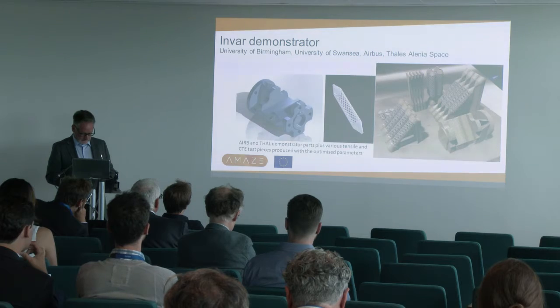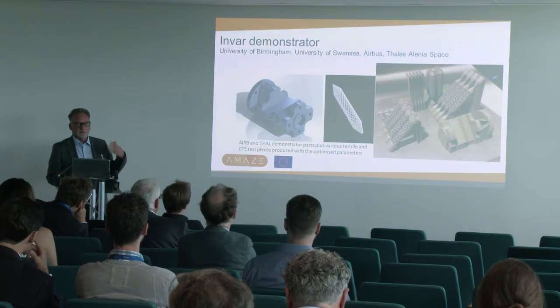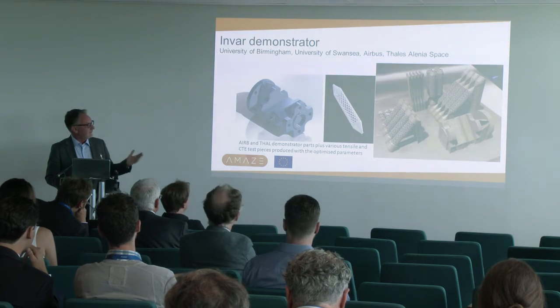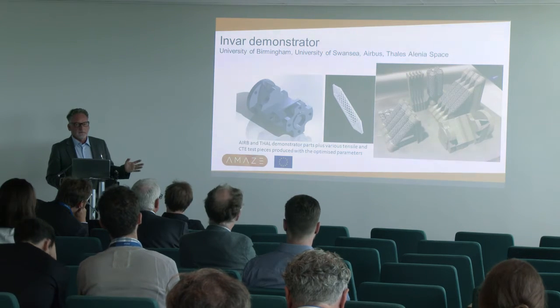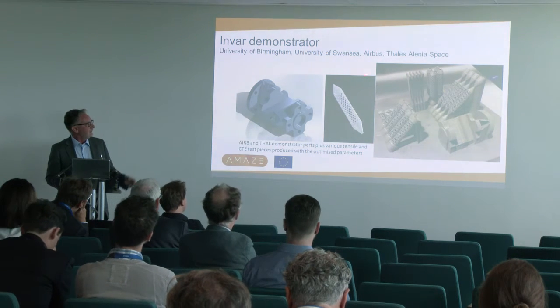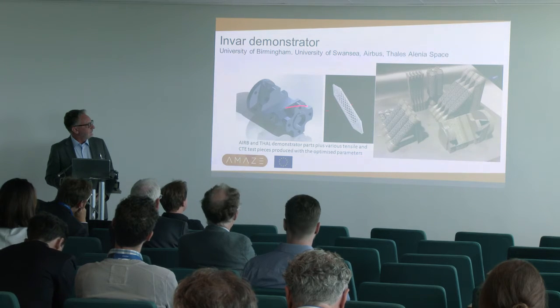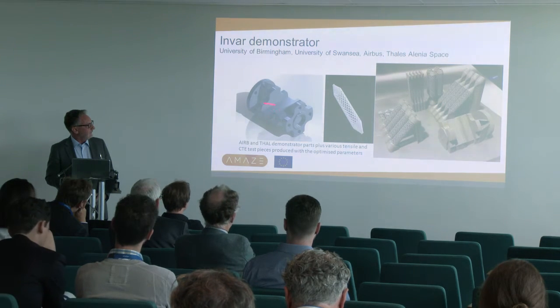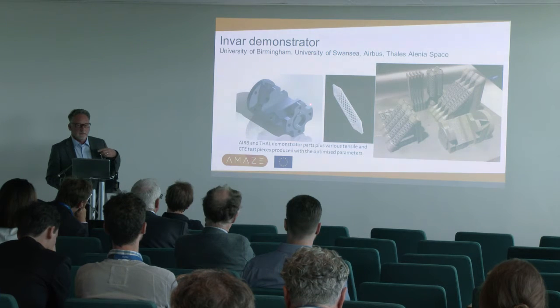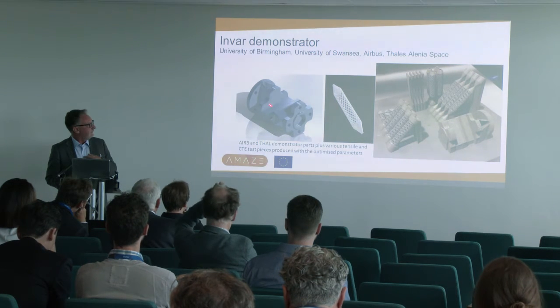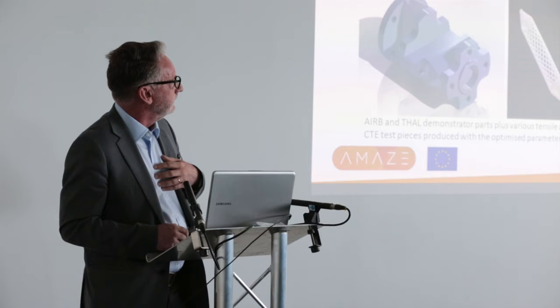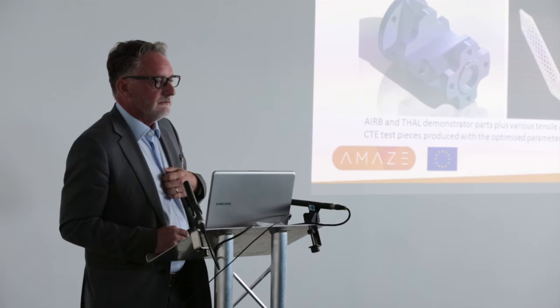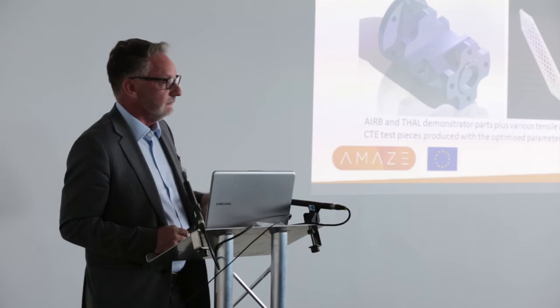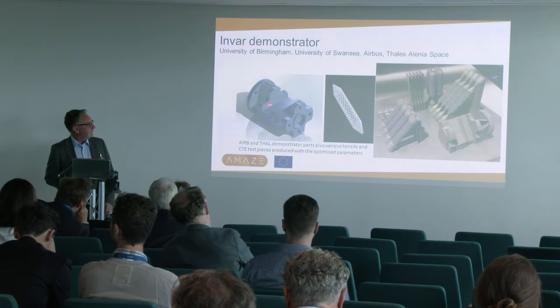So that work was then taken on. We were doing this preliminary work just at Birmingham, but it was taken on by the rest of the group who were interested in these INVAR materials. And we produced these different components. This is the part for Airbus, which is downstairs in the cabinet, and you can see that component. And some other parts for Thales, which they were interested in. So it shows the possibilities of processing with this material. And these parts actually went into a satellite component.